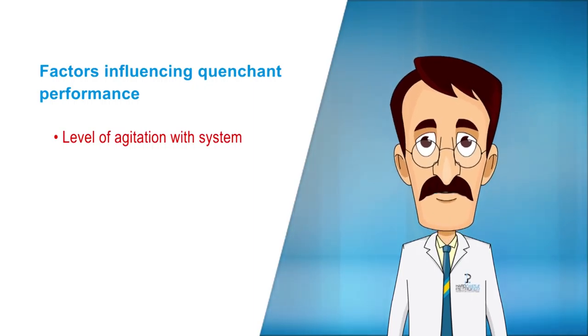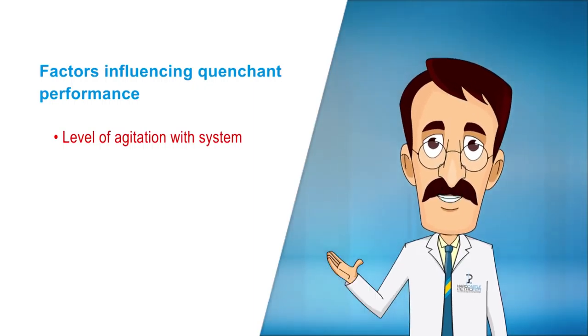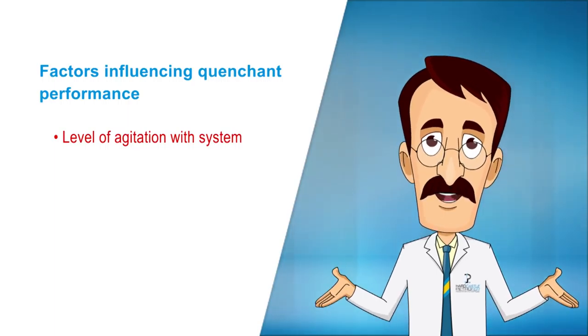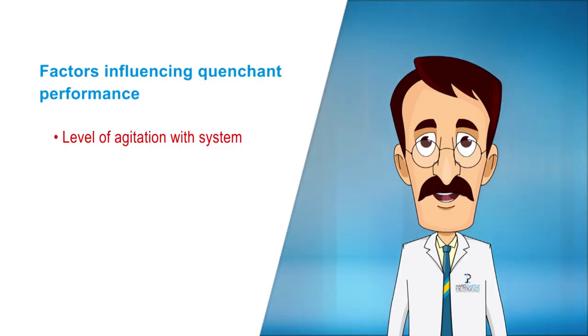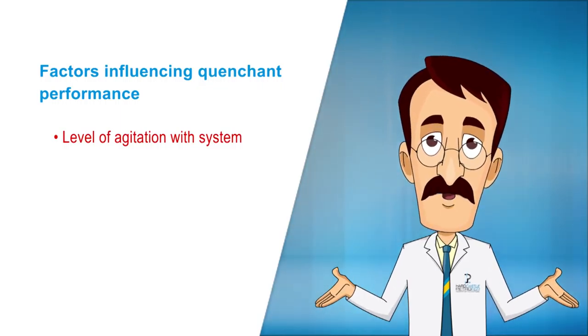The level of agitation in the system must not be excessive such that air is drawn into the oil. This condition will result in foaming and increased oxidation of the oil.